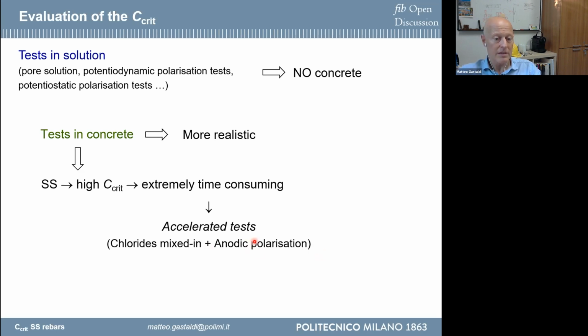Okay, so in accelerated tests you can add chloride directly during mixing, and this helps you have a controlled amount of chloride at the steel surface in a very rapid way, and then make an anodic polarization. So you use the circulation of current in order to increase the potential. This is the logic: in this way you get a fast idea of the initiation of corrosion of the reinforcement, because you increase the potential, so it's easier to have the initiation of corrosion.